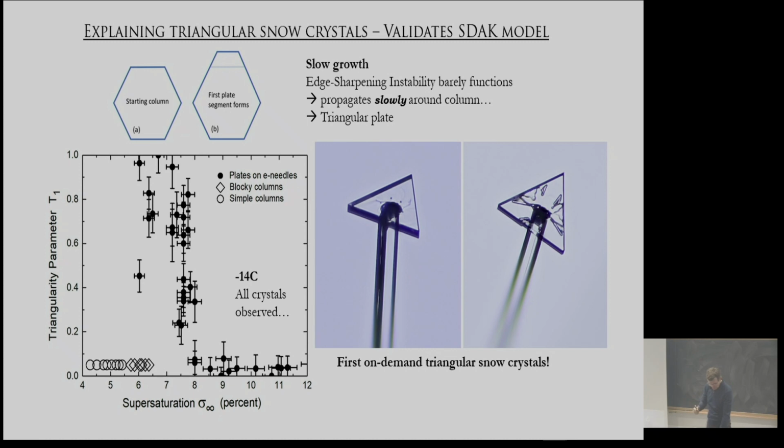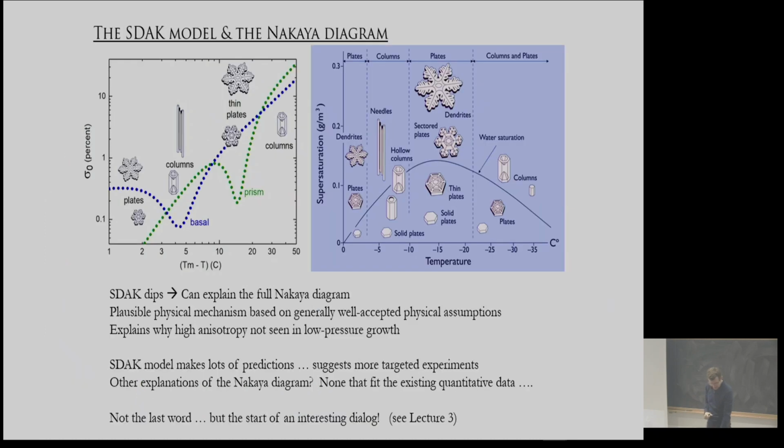So it's like, cool, good. What's funny is that the triangles don't stay. As soon as they get big, they want to truncate. You'd think that with the normal instability the tips would stick out farther, but that's not the case. You don't get anisotropy from diffusion. Diffusion likes round things.